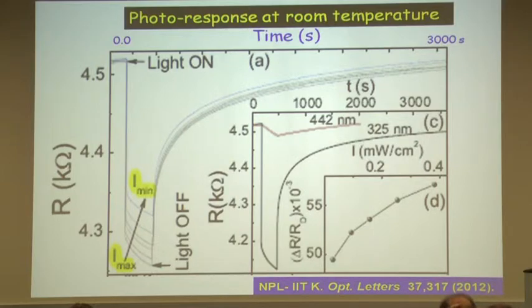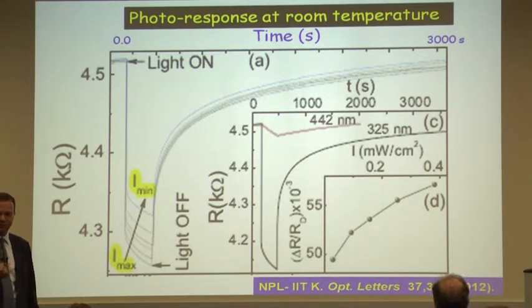On the other hand, if I use 325, you see this. So it's sensitive only to UV light. It's blind to visible light. All that photoconductivity is coming because of the UV light. And actually, the explanation is when you shine light, you are generating electron-hole pairs in the strontium titanate. Those electrons move towards the interface because of the electric field at the interface and contribute to conductivity.